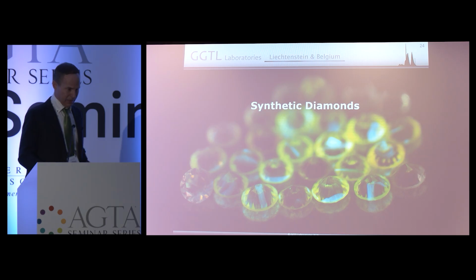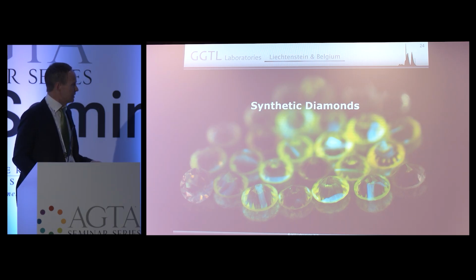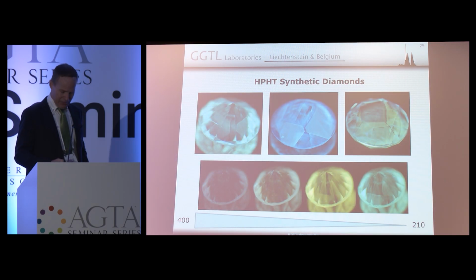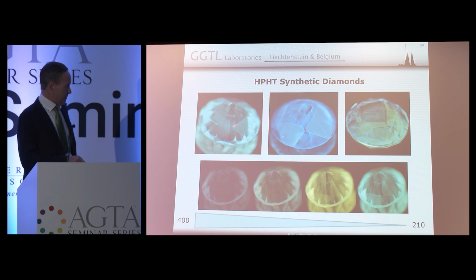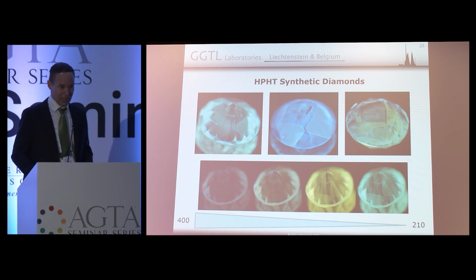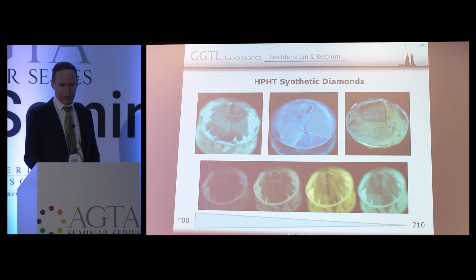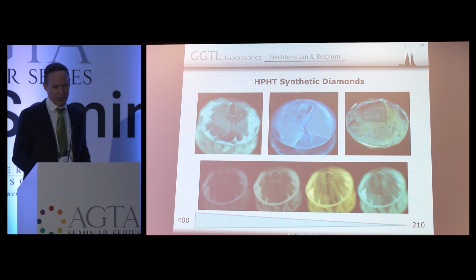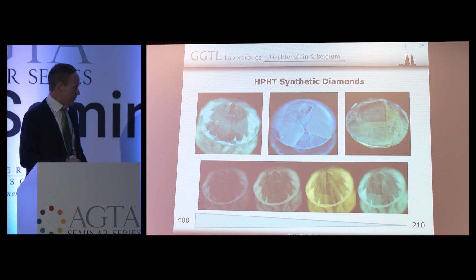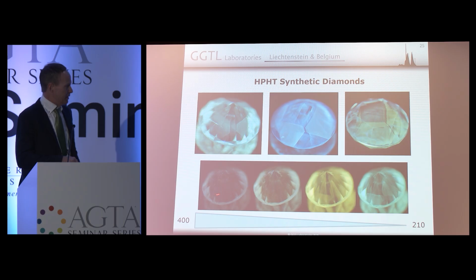So let's have a look at the synthetic diamonds and how they look. In synthetic diamonds, you have this. We have growth sectors just like in natural diamonds, but they are usually much more geometric. So you have these straight lines that separate octahedral from cube and other faces, but the most common is the cube face and the octahedron in the HPHT synthetics. So you always see these things. To visualize this, unfortunately, you do need deep UV. This doesn't visualize well on the short wave. You can see it down here in this sample.